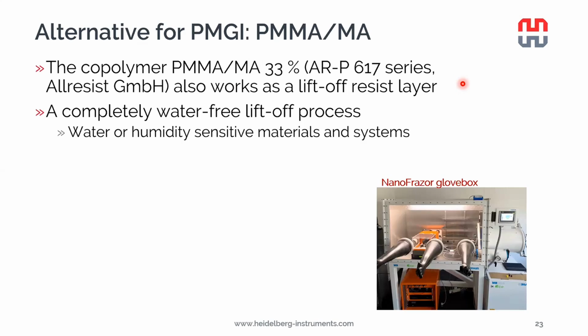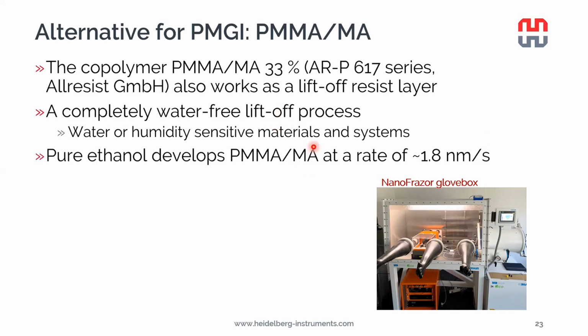But why did we look into this material in the first place? Well, we have quite some requests from our customers who would like to carry out the entire device fabrication process in a completely humidity-free or water-free environment. Basically, a glove box, which we have developed, a custom-made glove box with MBraun. And we need the PMMA MA for carrying out a completely water-free lift-off process. So it turns out that it can be developed with pure ethanol at a rate of 1.8 nanometers per second. It's actually just by chance perfectly suitable for our thicknesses of materials we are dealing with here.